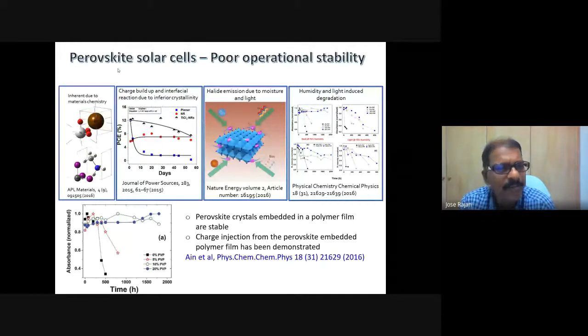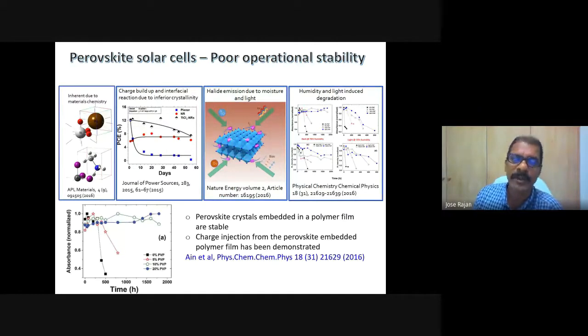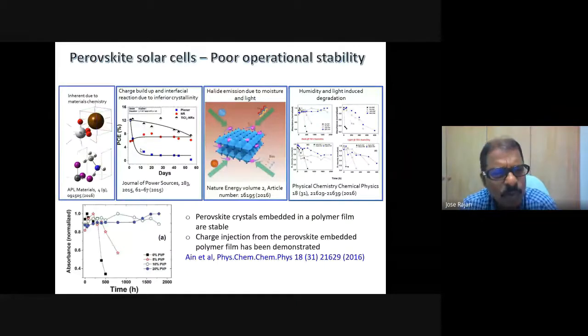From our nanorod solar module, we have shown that there is probably ion migration between the perovskite and the electron transport layer, to which the electrons are injected from the perovskite. We have shown this when we use highly crystalline nanorods, which are dimensionally much bigger than the corresponding nanoparticles. Our nanorods are about 100 to 200 nanometers wide and a few microns thick, so we can consider them a bulk material, and most of them were single crystals. When we have that single crystal electron transport layer and compare the variation of efficiency with time of perovskite made on single crystalline and nanocrystalline layers, you will see that the nanocrystalline perovskite decays very fast.